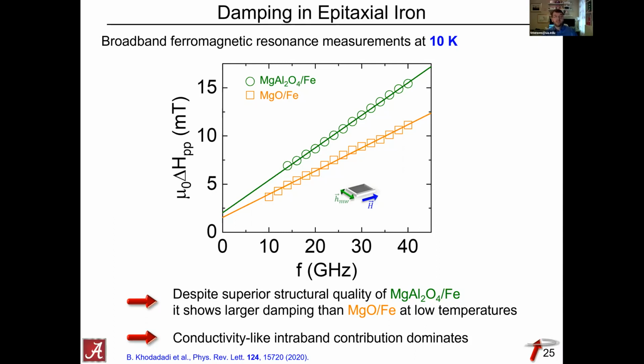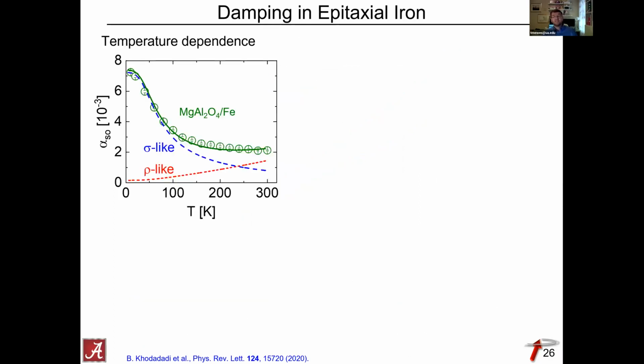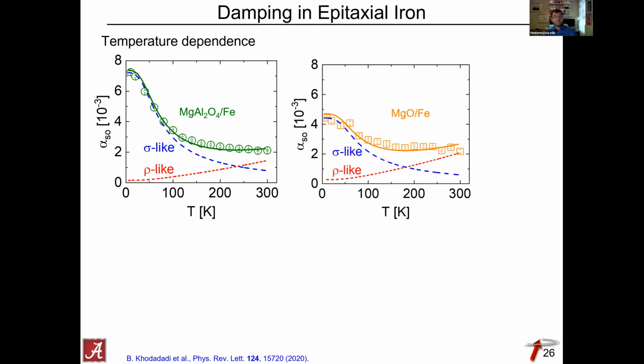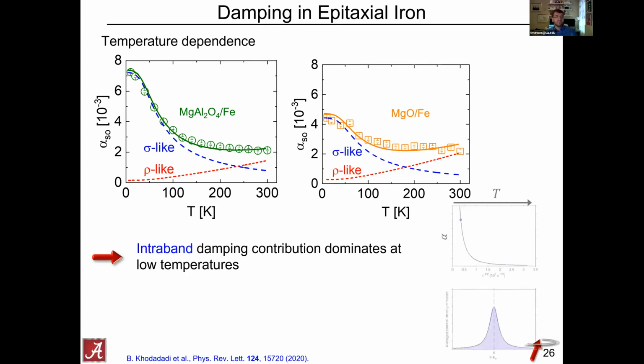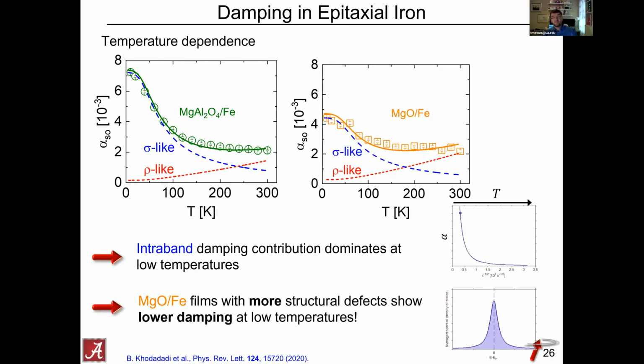You can obviously do these measurements at a whole bunch of temperatures. What you get is that for the film on magnesium aluminum oxide, you can clearly see that at low temperatures the damping increases, just like the conductivity increases in this kind of film. If you compare that one-to-one with a film grown on magnesium oxide, you see that this increase, while you might still see it in this particular film, is significantly smaller than in the film with a higher structural quality. Again, the reason is that we're not limited by interband contributions, but rather by the intraband damping contribution, which dominates at low temperatures.